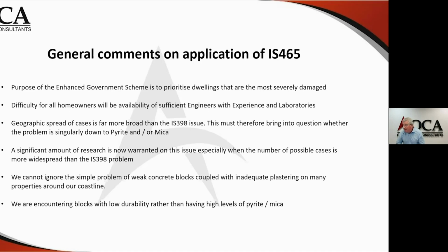The difficulty for all homeowners will be the availability of sufficient engineers with experience and laboratories. Again, a lot of these properties are going to have to be tested. Not all of them, but yes, some of the local authorities have been requesting secondary evidence of expansion or of the expansive products. And again, in my mind, that is reasonable so long as they don't do it for every single property. So if you have a housing estate and you have already tested 3 or 4 or 5 houses within that, and you can see that you've got elevated levels of total sulfur or elevated levels of mica, and you can see that there has been deleterious breakdown, as in you've got the breakdown of the concrete block purely as a result of mica, but you're not going to see any secondary byproducts from mica because it is a physical breakdown product. Or with pyrite, yes, you will see gypsum, or you certainly can test it from a chemical perspective and see elevated levels of acid-soluble sulfate, which would give you a good, clear indication that there has been pyrite degradation and that expansion has occurred.